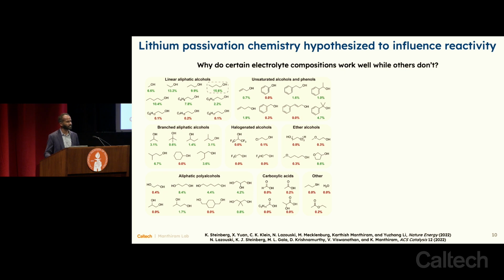We tried hundreds of experiments, trying different solvents and different proton donors, and putting up here a sampling of data showing the Faradaic efficiency for different proton donors in this chemistry. And honestly, we really just couldn't make sense of this. This looked about as random as could be. We continued to make hypotheses. We would do 10 more experiments. We'd look at the data again. We'd come up with a better hypothesis, and we would try again. And we continue to march through, finding no success whatsoever in explaining why certain proton donors and certain solvents worked well for this chemistry.